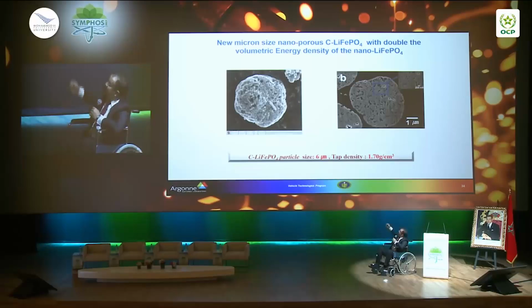And the idea is when you fill the electrode with the electrolyte, these pores will be filled with the electrolyte, and therefore lithium, instead of going all the way through, will come here and fly very fast out of the material. So you should get very high energy without affecting the power performance of this material.